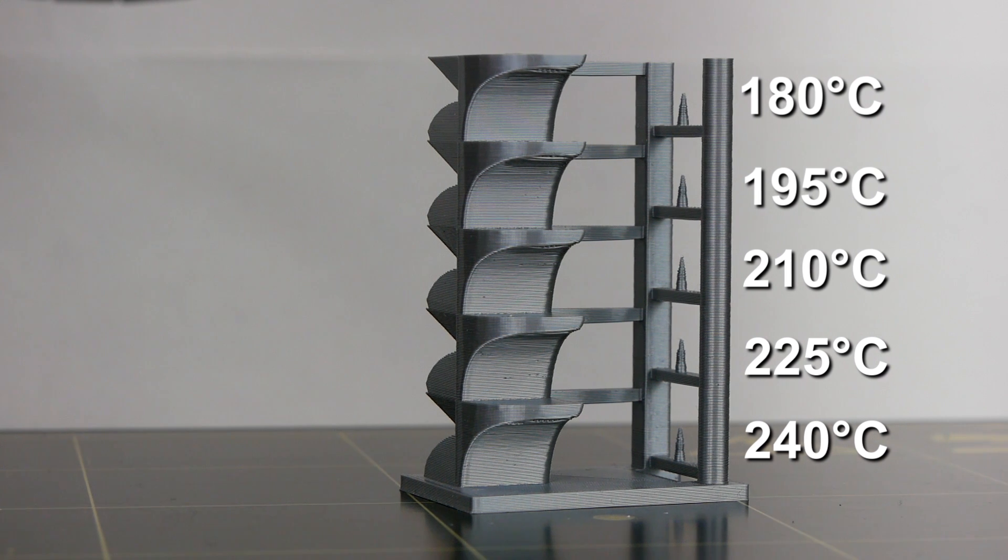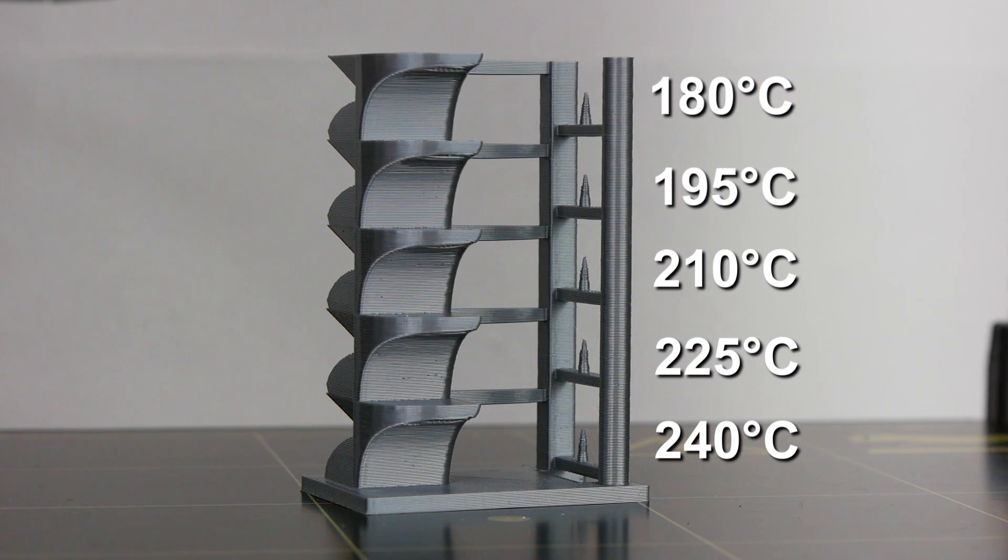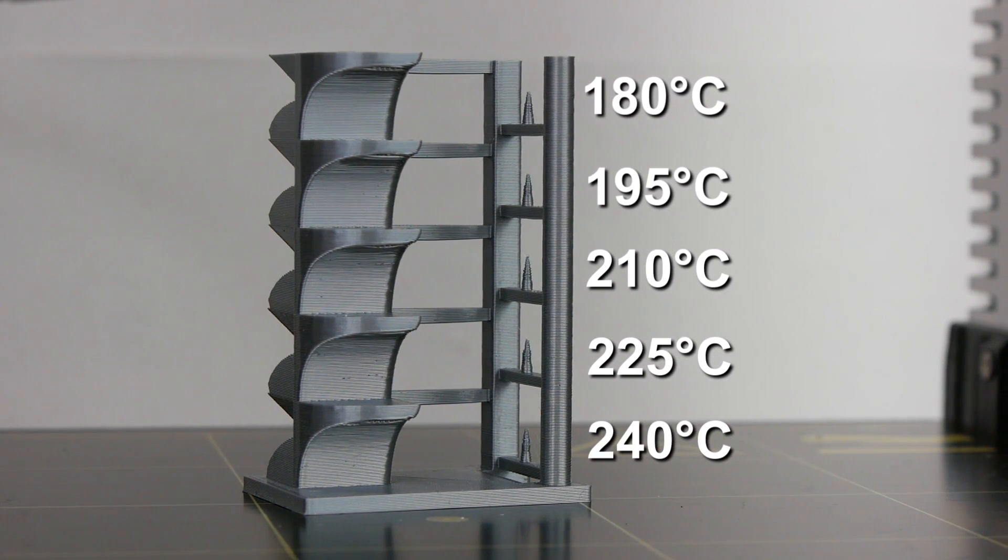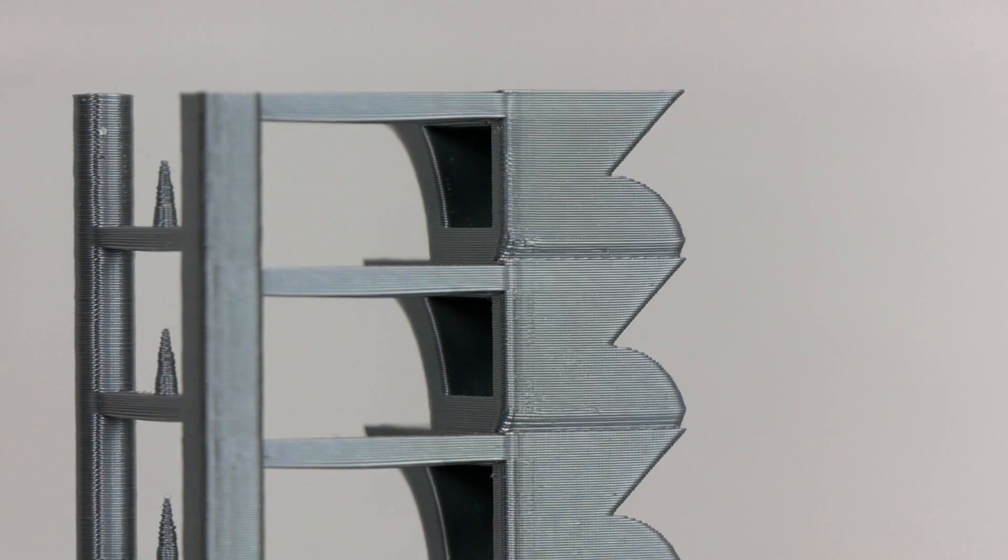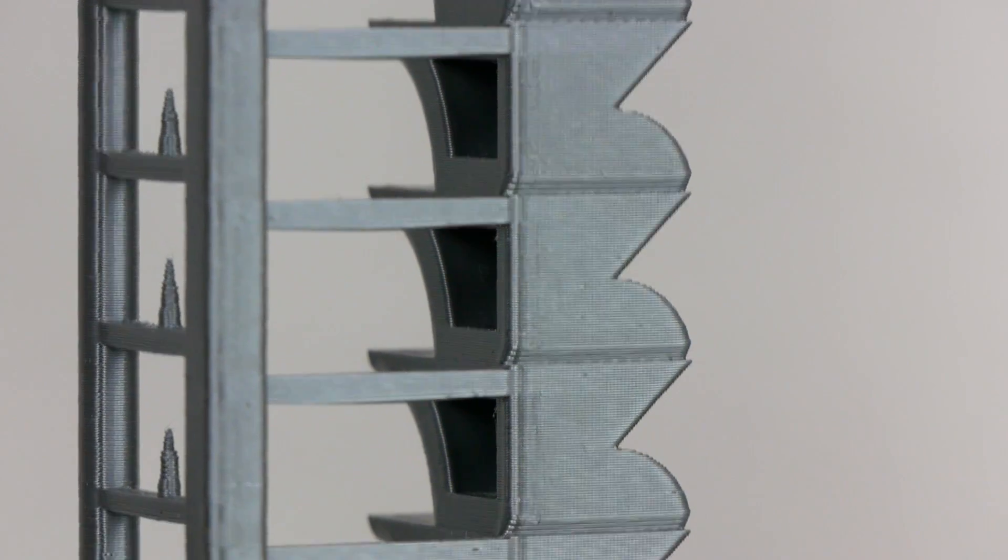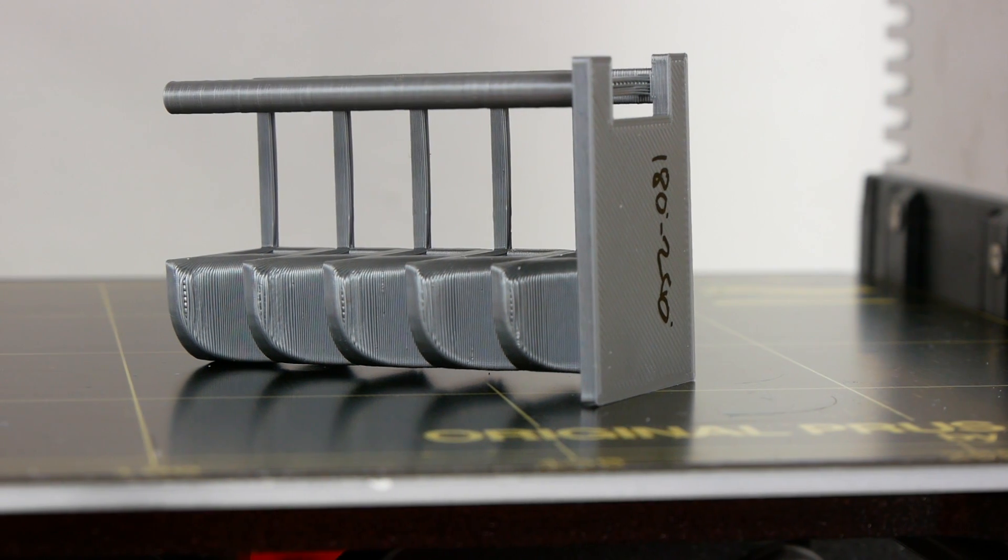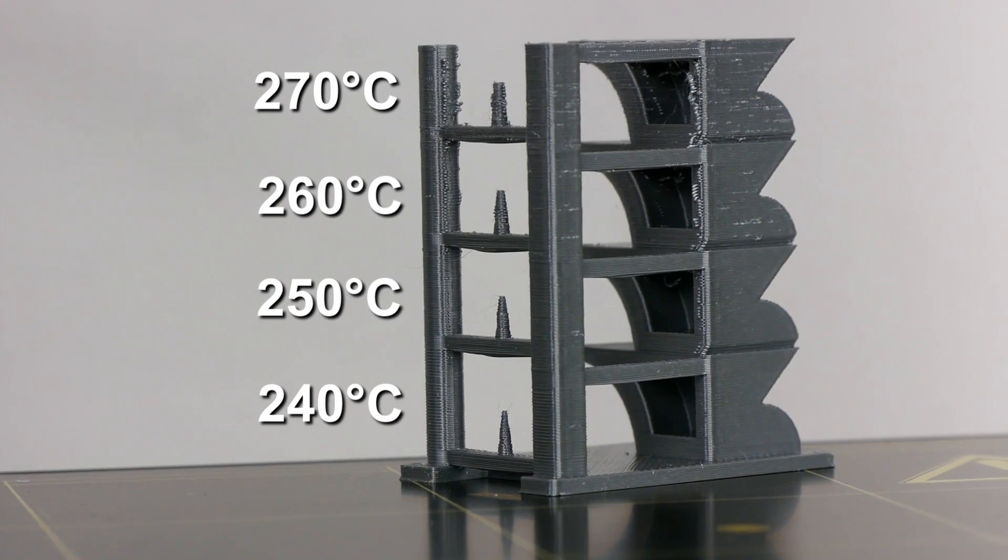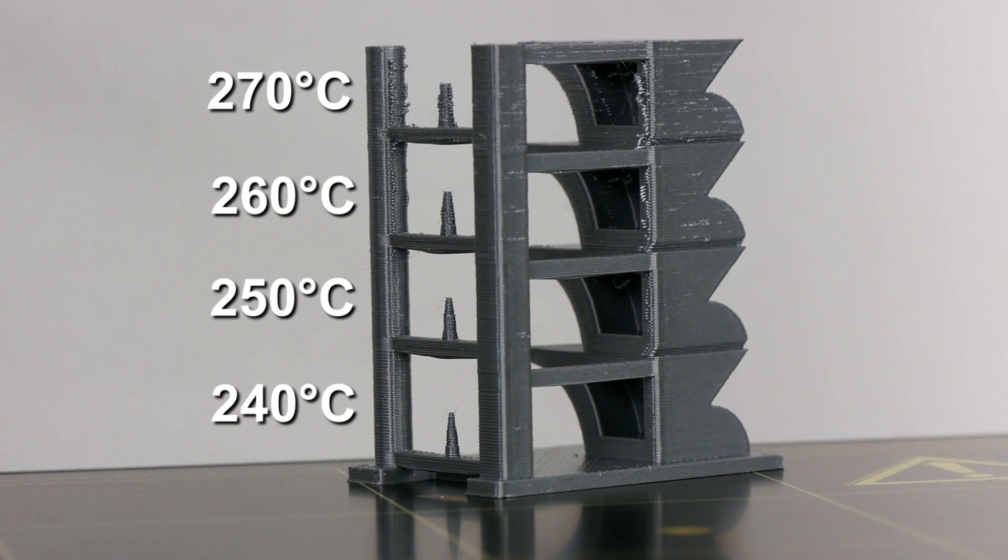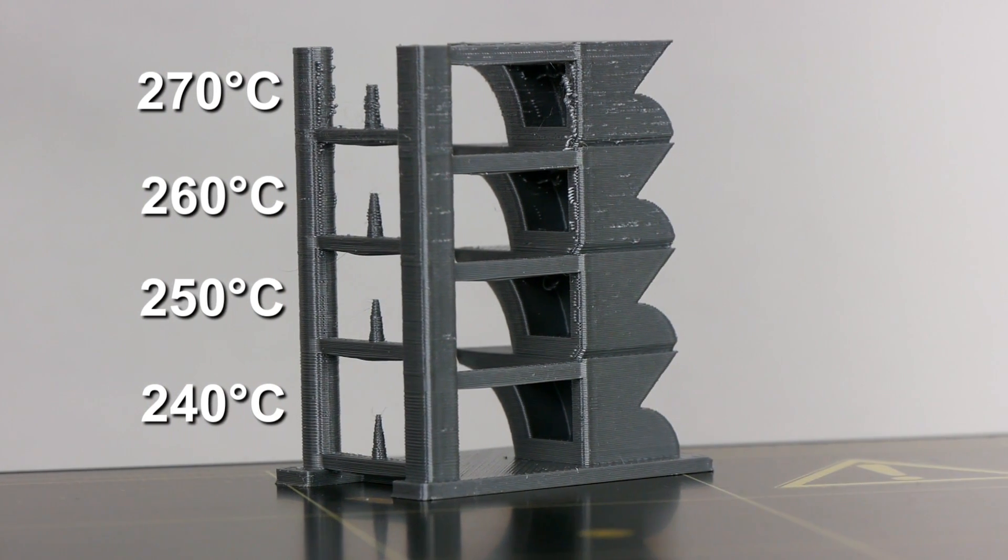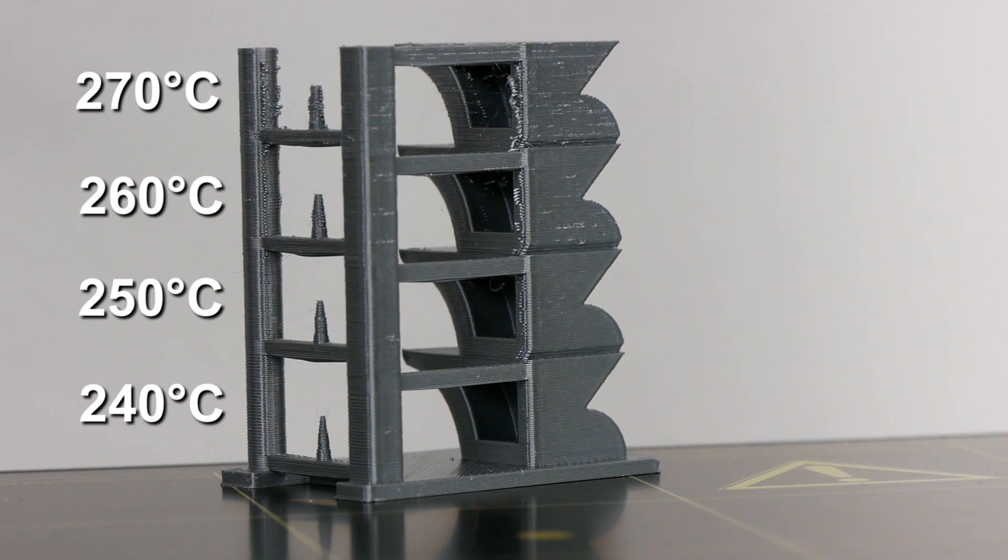So in order to see a difference, I increased the temperature range from 240 degrees Celsius down to 180 degrees in 15 degree decrements. This print still looks fine, but you're able to see a little bit of bubbling at the highest temperature and some small printing defects at 180 degrees. I still wasn't 100% satisfied, so I printed a third test at temperatures from 240 degrees to 270 degrees.